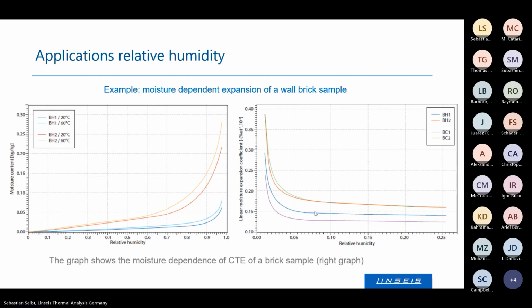At higher temperature, the effect was a little bit shifted, but similar. At lower temperatures, it was also the same effect. You see that the expansion of the sample was heavily influenced by the humidity level.